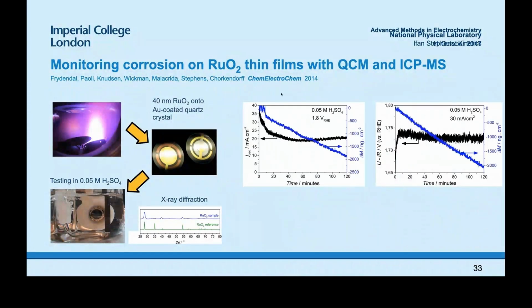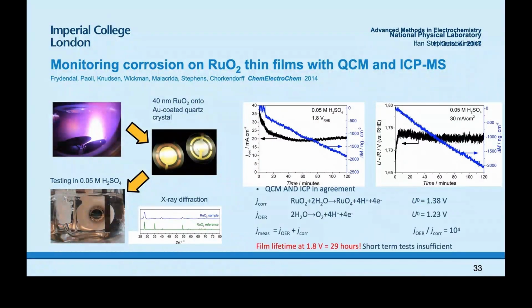However, when we measure the mass losses using the quartz crystal microbalance at the same time, we see that even though we have a very stable electrochemical response, there's a constant loss of mass on both surfaces. This is equivalent to about 1 nanometer per hour. So even though the actual corrosion current is about 4 orders of magnitude lower than the oxygen evolution current, a 40 nanometer film would only last about 30 hours.